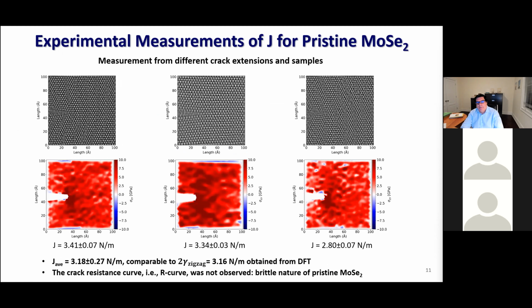Here is another example. In the previous slide, I showed you molybdenum disulfide. This is molybdenum diselenide. It's another of those transition metal dichalcogenides, and there are many alloys that you can generate. But the message I would like to convey is that, again, we have quite a uniform measurement of the energy for propagating the crack, and that the value is very similar, in this case even more similar to a Griffith type of criterion.